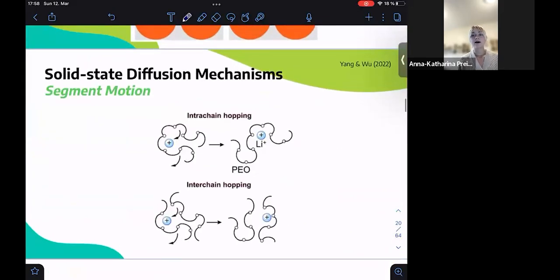And lastly, for polymers, we're looking at something called segmental motion, which really relies on the mobility of the polymers in order to facilitate the movement of the ions throughout. In this case, we have polar groups within the polymer, which enable transport. And the ions will basically hop between the coordination sites along the polymer chains. In this case, the rate of ion transport is directly related to the concentration of the ions and the segmental mobility of the polymer chains. Typically, this segmental mobility occurs around the glass transition temperature.